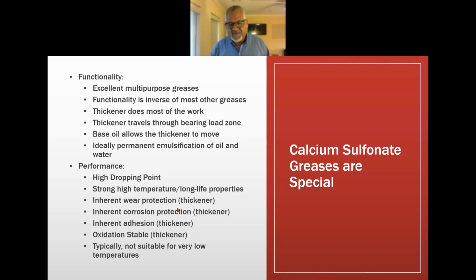Inherent wear protection in the thickener. I mentioned earlier calcite particles, calcium carbonate. You get inherent corrosion protection from the thickener. It's polar. It sticks to metal. It's a modified detergent. Inherent adhesion from the thickener because of the polar nature of the thickener. And I don't want to mislead you: there are polymers or tackifiers in most calcium sulfonate greases that I know of, but inherently very good adhesion. Oxidation stability is really great because of the thickener. Now, if you want the best oxidation stability, you still have to add oxidation inhibitors to the base oil.